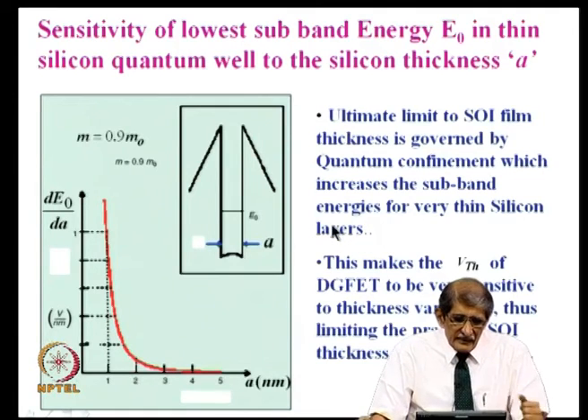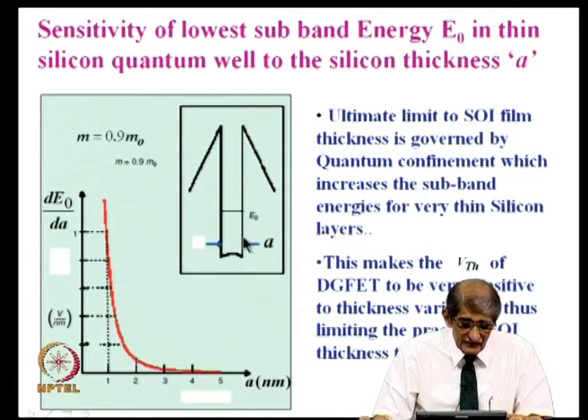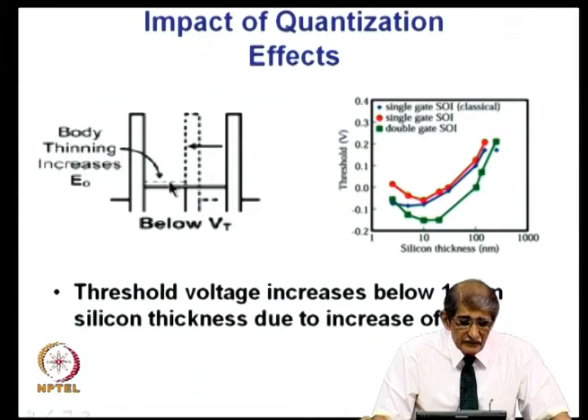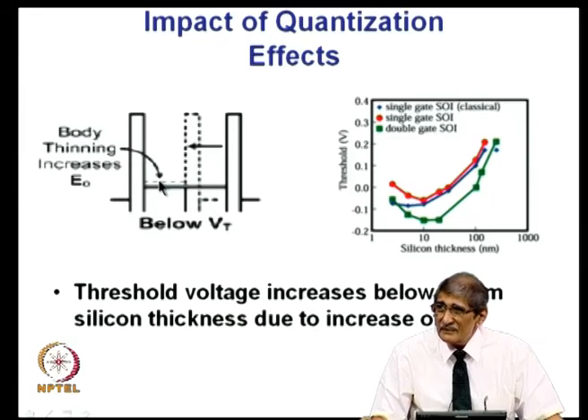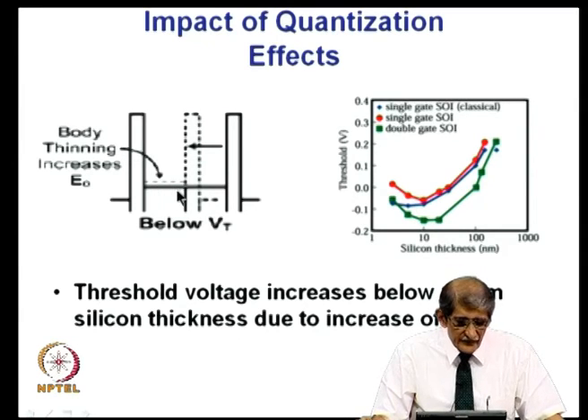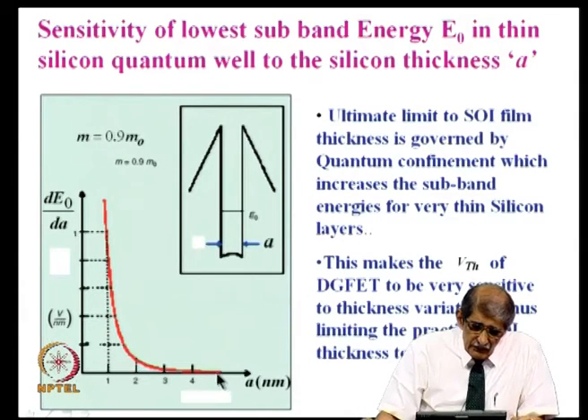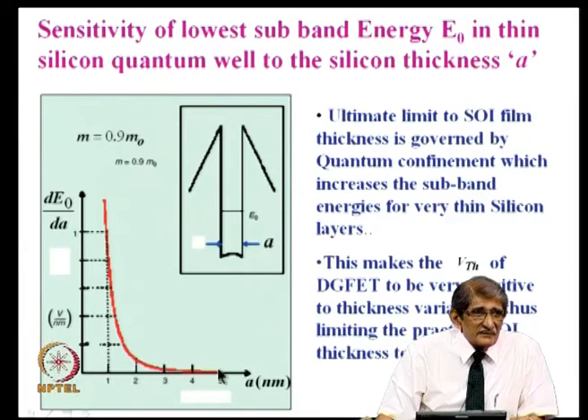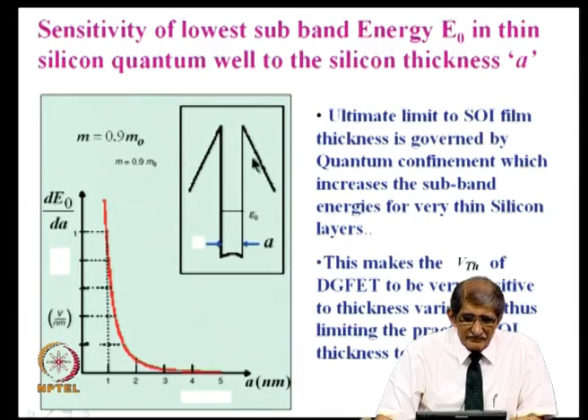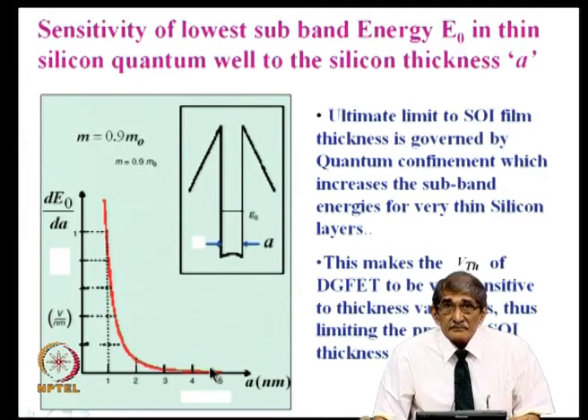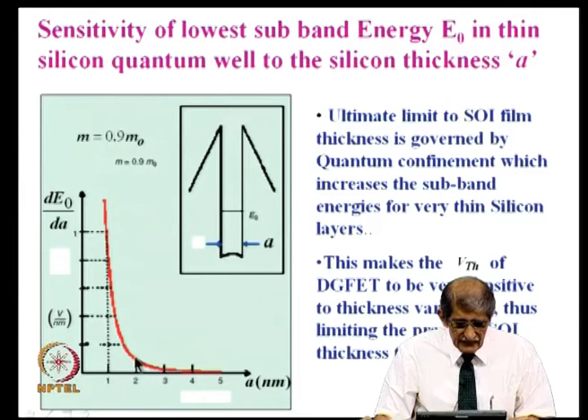So, now they have worked out some theory on that, analyzed it using the quantum analysis. This delta E naught, how much is that delta E naught? It is a measure of how much is the shift in threshold voltage. So, the delta E naught, what they have seen is up to about 5 nanometers, not much change in delta E naught, it is there. But if I reduce this thickness, I put it as A, it is T silicon, this is oxide band gap, conduction band of oxide is here. If I reduce this thickness, keep on reducing, bring it below 4, 3, 2, etcetera, below 3 nanometers,